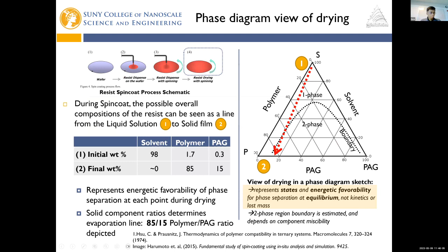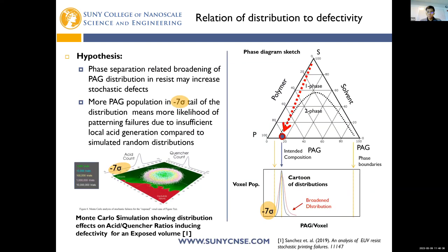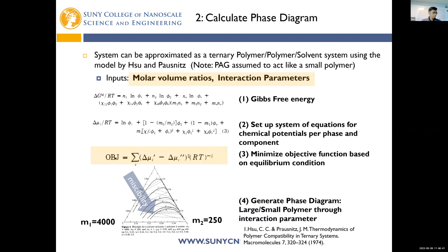So what I presented on was basically a phase diagram view of drying to try to understand if we get extra miscibility difference, basically energetic favorability of phase separation when we enter a two-phase region, because that's basically in spin coating. As you dry, you'll get rid of your solvent and only have polymer and other components left. So I related this to basically the distribution and how it could potentially broaden, as well as some